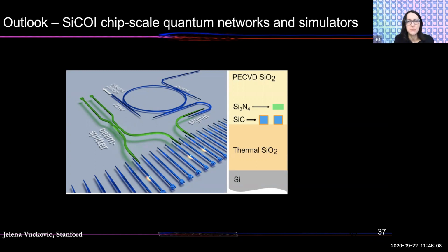I already showed you some of the tuning methods that we have. We can achieve that level of reconfigurability by doing, for example, second layer of lithography, identifying for quantum network applications as an example, where the high quality quantum emitters are, and then wire them using a network of photonics that we implement on top. And we can do that in silicon nitride on top of silicon carbide as an example.